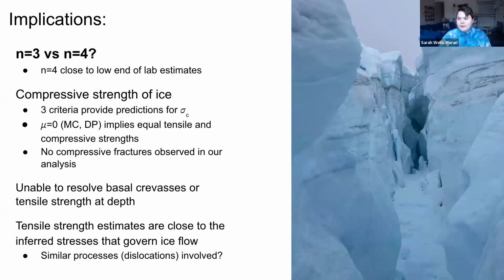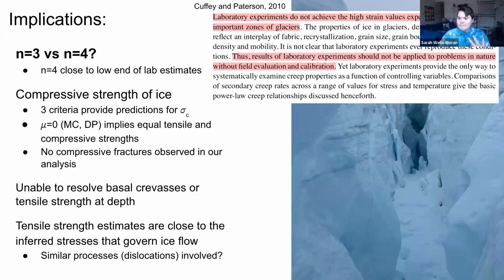So some implications, n equals 3 versus n equals 4. What's really interesting is that the predicted values of tensile strength for n equals 4 are within the low end of laboratory estimates. When I was starting out in the field, I was reading a lot of papers and a lot of textbooks, and a lot of them were very skeptical about whether or not lab estimates could be applied to natural settings. I've taken this screenshot of Cuffey and Paterson where it says laboratory experiments don't achieve the high strain values expected in dynamically important zones of glaciers, and thus results of laboratory experiments should not be applied to problems in nature without field evaluation and calibration.